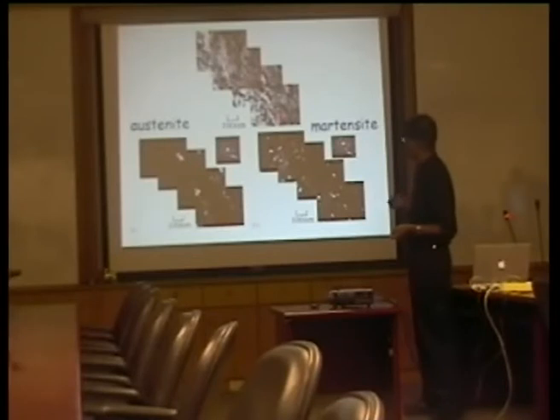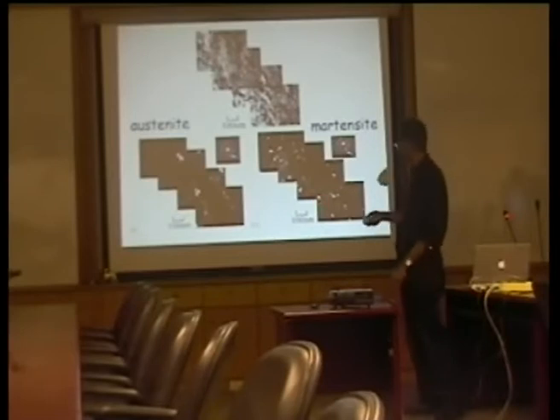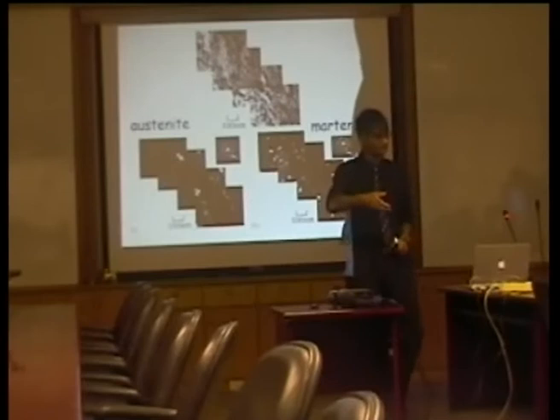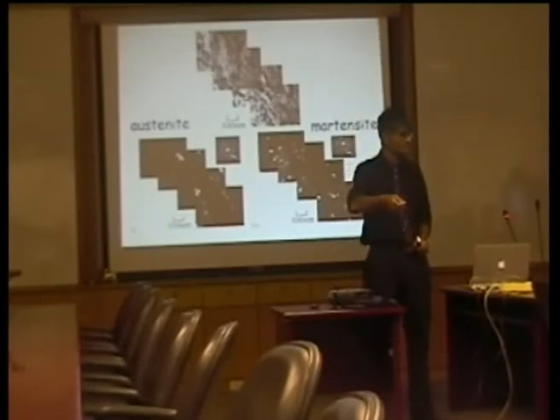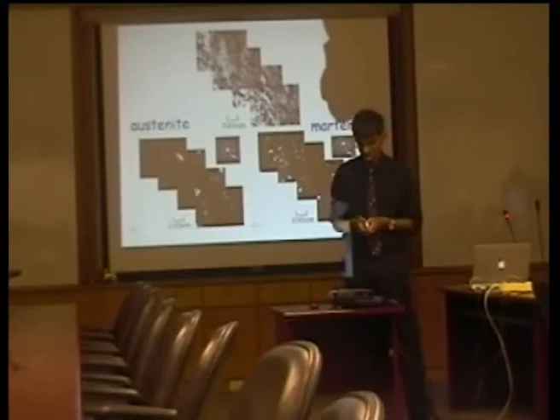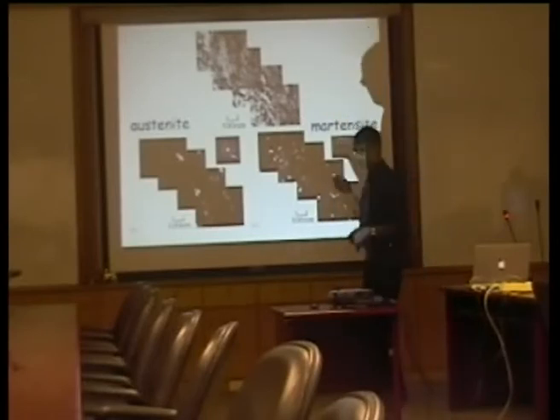So this is the longitudinal section again. If you take a dark field image of austenite, then we see long grains of austenite, because the region here has the same orientation as the region here. If we now take a dark field image of martensite, then we don't see continuous cells, but we see discrete cells, because each grain of austenite can transform into many, many different orientations of martensite. Yeah. So even though we had a strongly crystallographically textured material, when it transforms, we can remove that texture effectively by forming many, many grains of martensite in different orientations. Extremely difficult microscopy.